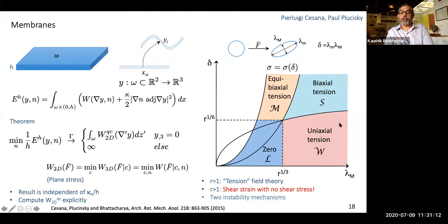There's a region where you have a structural or wrinkling instability, and there the state of stress is necessarily uniaxial tension, even though you have stretch in two directions. The stress in one direction is necessarily zero. Then there's a second region where you have fine scale material microstructure, analogous to the stripe domains that I showed you earlier. And there the state of stress is necessarily equibiaxial tension. In other words, you have no shear stress despite the fact that you have shear strain. So here you have a solid, but because you have microstructure formation, it behaves like a fluid in this region. And there's a region where it behaves like a solid.